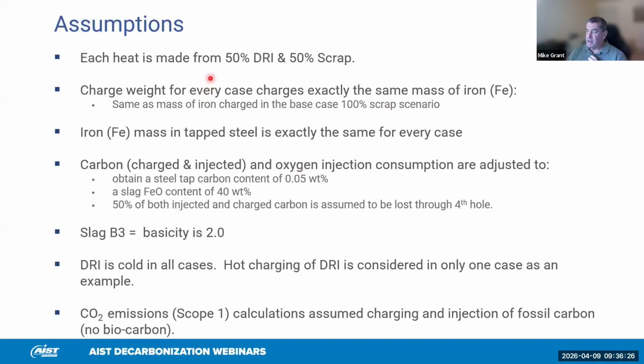All heats that I'm simulating assume 40% FeO content in the slag and 0.05 weight percent carbon tap. And each heat is 50% DRI, 50% scrap. We're charging exactly the same number of atoms at the beginning into the furnace, and we're tapping the exact same number of atoms when we tap. We can do this in a theoretical exercise, and the purpose is to show how we balance the carbon and the oxygen to maintain exactly the same yield. A theoretical exercise, but it's always good to know for evaluating these cases.